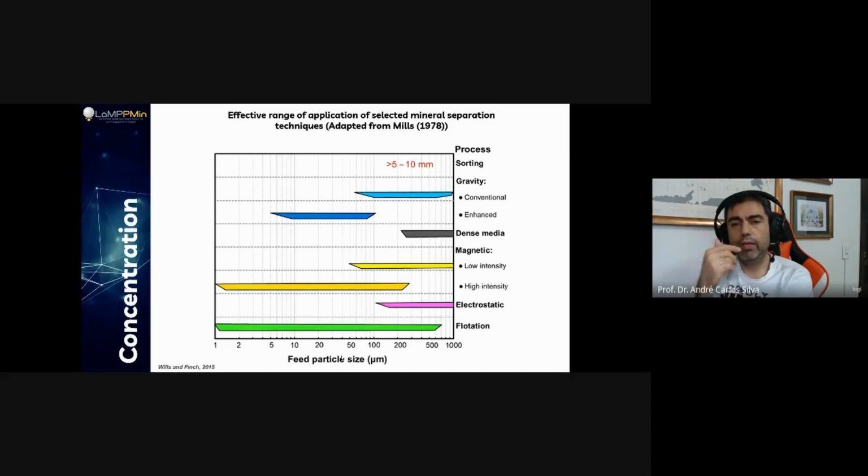And after that, we can also send the material to XRD. Since we have only two minerals in association, because we can take a look at it and say, okay, there are just two minerals here, or it looks like just two minerals, we expect to have a great result from the XRD. Because when you take a look at the XRD spectrum, if you have plenty of minerals, you end up not being able to see anything. And if you have a lot of quartz, then you take a look and you only see quartz, okay? But if you can actually sort your minerals, oh, I'm going to take this one and there are no sulfides in this one. Yes, it's pure gangue mineral.